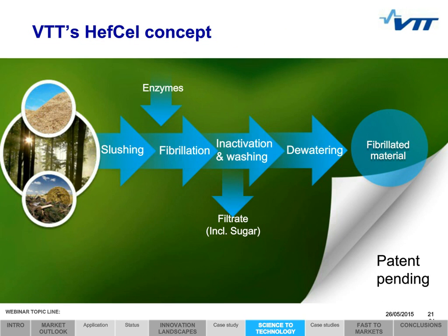And in HefCel, there is no separate enzymatic treatment stage, but the fibrillation takes place due to the combined effects of the cellulase enzyme and the mechanical action. After the fibrillation stage, the enzyme is inactivated by steam. The material is washed and the filtrate containing sugar is recovered. The sugar is a valuable byproduct of the process and it can be utilized, for example, by the chemical industry.